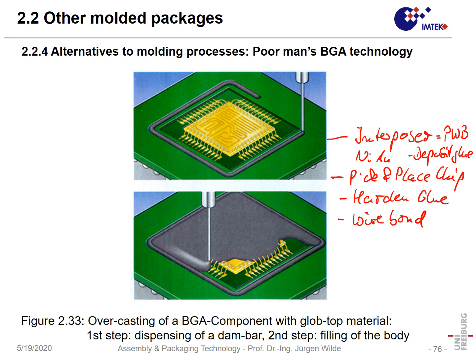We take a syringe, and in that syringe is a liquid molding compound. In fact, it's not called molding compound, but it's a so-called glob top material, but it's a molding compound that is liquid at room temperature. Then we deposit a ring of that material around our chip, and then this ring is filled up with a complete layer of our glob top material. So we deposit, and then we harden. Advantage is no tool, and all of the design is software designed.